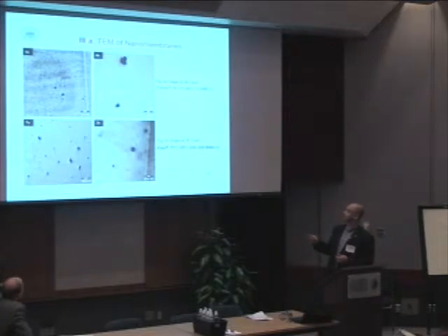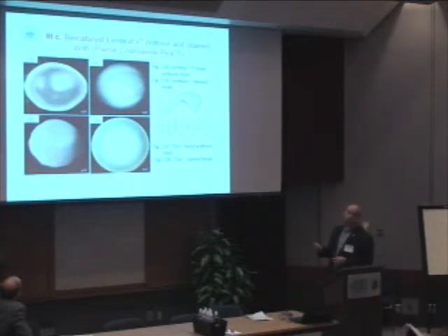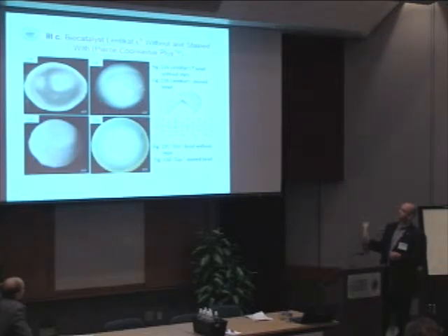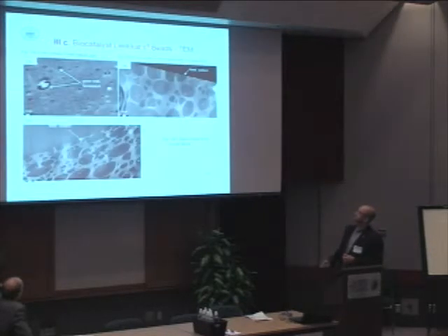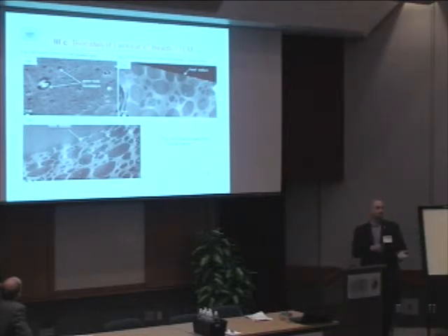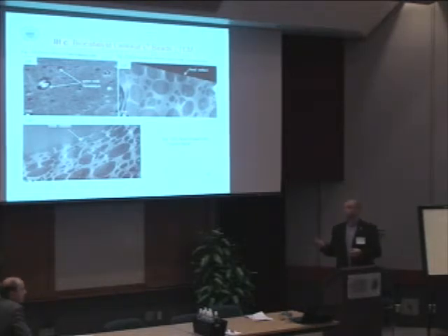With the systems we're developing, we're getting very good lifespan from the membranes. On the other side is getting immobilized biocatalysts into our reactor systems. We're working with LentiKat's, a European company, studying how we immobilize enzymes in this type of bead — about five millimeters in diameter. Looking at electron microscopy cross-sections, you tend to see areas of high density protein (the enzyme) and other areas that are not high density, meaning we're not getting optimal distribution of our biocatalyst even with standard industrial technology.